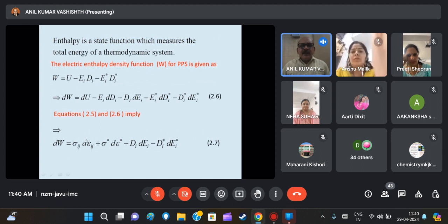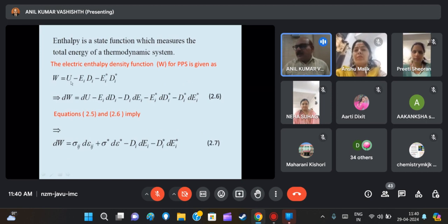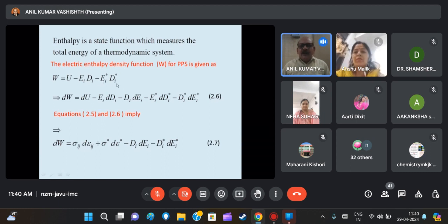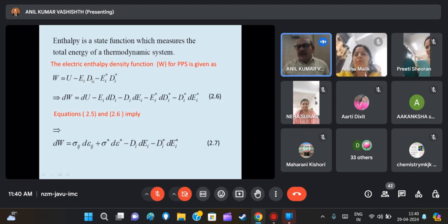After modification, the enthalpy function was calculated, and W was found as the internal energy minus the work done by the electric forces, Ei Di and Ei star Di star. I am using tensorial notation instead of vector notation. If you are used to vector notation, then it is the dot product of E and D, and similarly E star and D star, like that.